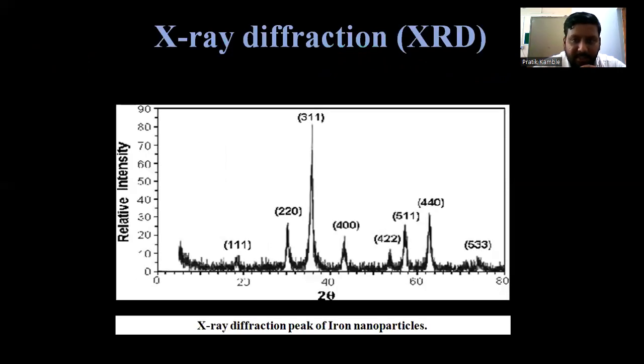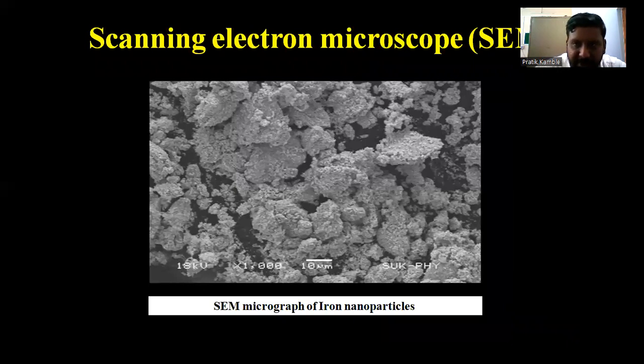Then X-ray diffraction, which is XRD, we can observe the physical property of that particular synthesized iron nanoparticles by this XRD. These peaks were compared with the standard JCPDS file of iron nanoparticles, and we have concluded that the synthesized nanoparticles are iron nanoparticles. Then scanning electron microscope, which is SEM, a method for analyzing the size and shape of that particular synthesized iron nanoparticles. We can observe here that the synthesized nanoparticles were spherical in nature. They were agglomerated, and the size of nanoparticles ranged between 50 to 80 nanometers.